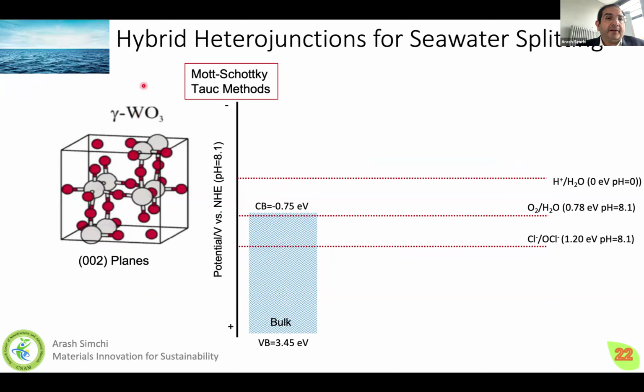What we do, we use tungsten oxide because, as you know, tungsten oxide, especially gamma type, has a very active surface area in (002) planes. And it's really a stable material. And it's really cheap, well, not really cheap, but it can be processed very easily. The problem is tungsten oxide cannot be used for seawater splitting. And why?